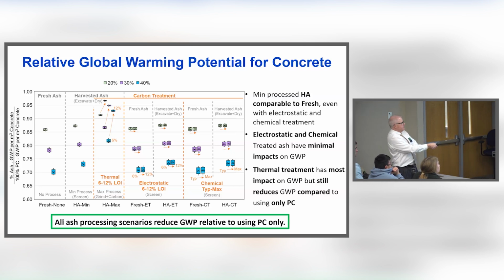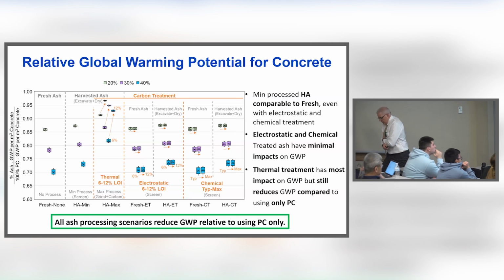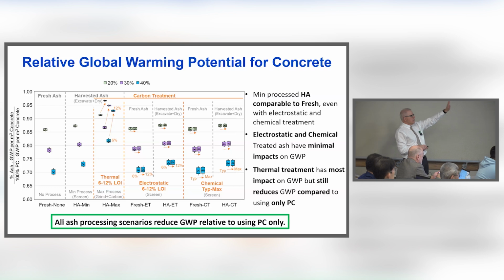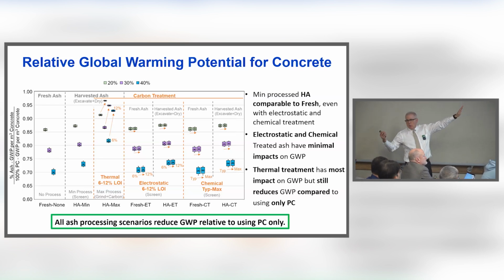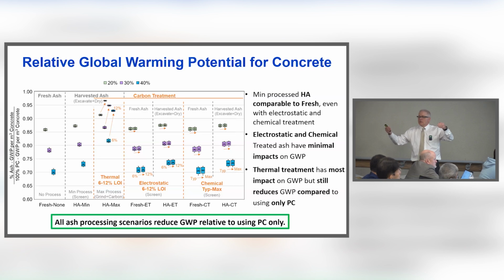But we're looking here on the x-axis at different options like I showed in that previous slide, and then the y-axis is the ratio of the greenhouse gases associated with a meter cubed of concrete with one of the ash percent replacement options being considered, relative to the greenhouse gas emissions for producing concrete with cement alone, no ash in it at all, all right? So if that ratio is less than 1, that means what? If the greenhouse gas emissions for making concrete with ash in it, normalized by concrete without ash, is less than 1, what does that tell us about our greenhouse gas emissions? It's lower, right? If it's less than 1, it's beneficial. That's a good thing, right?